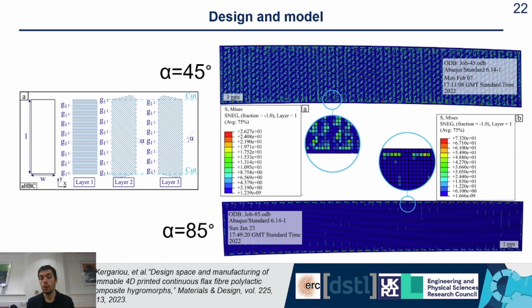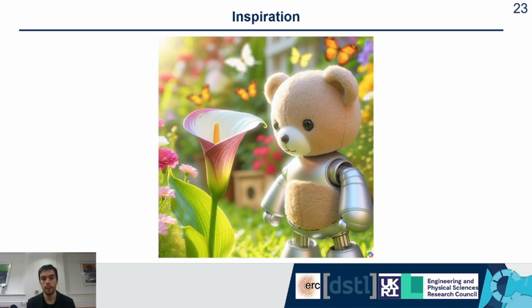And so you understand what is the link between your geometry, your printing path, and the actuation you obtain at the end. For the 45-degree specimen, for instance, you see that the actuation comes from a bit everywhere in the specimen, whereas for the 85, it's much more distributed on the edges, the high stresses that create the actuation. And so that's also one of the benefits of this model.